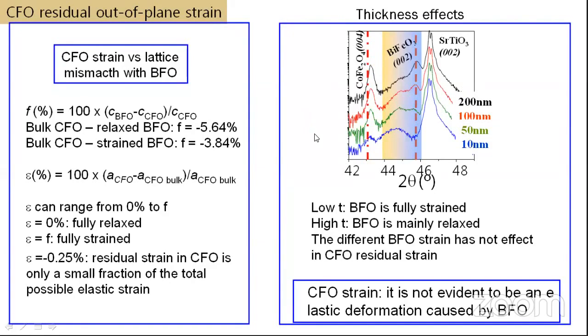Now, how the strain varies when you vary the thickness of the film. If the film is 10 nanometers thick, you can see only the strained bismuth ferrite occurs. This is the perovskite phase, only the strained parameter occurs. When you increase the film thickness, slowly the relaxed portion comes out, and for films above 200 nanometers, you can see the film is completely relaxed and the strained portion is missing, or a very, very small strained portion. But the cobalt ferrite remains as such, compressed.